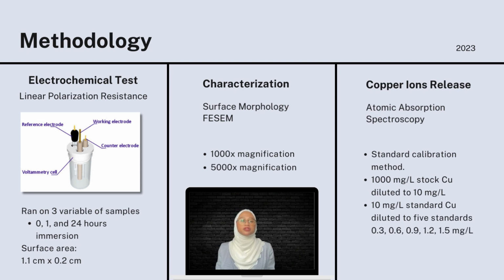The analysis was run on 5 standard copper and 3 sample solutions that have been variably immersed with copper coupons. The 5 standards were prepared from 1000 mg per liter stock solution of copper, diluted to 10 mg per liter, which was then diluted again to 0.3, 0.6, 0.9, 1.2, and 1.5 mg per liter of concentration.